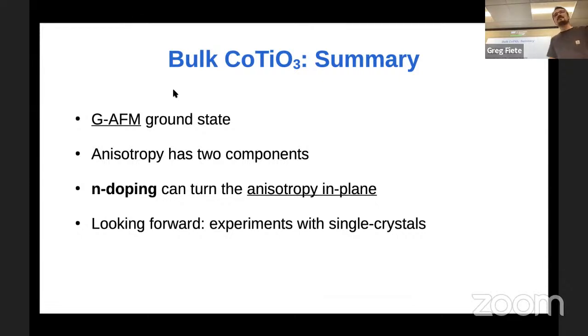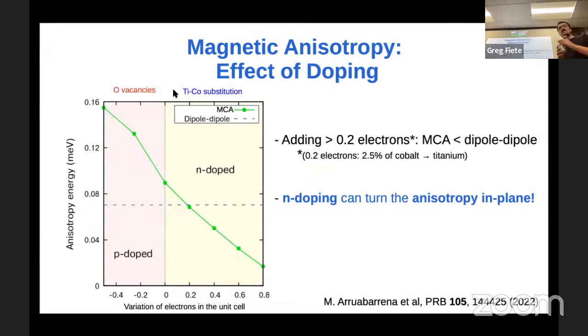Yeah, sure. So for the case where you N-dope it to turn the anisotropy in plane, are those numbers roughly consistent with experiment, for estimates of the doping level? The doping level of 2.5%. Yeah, so 0.2. Well, okay, so I guess the question is, the magnetic anisotropy, that dashed line there, which is around 0.2 electrons, is that consistent with what's measured in experiment?